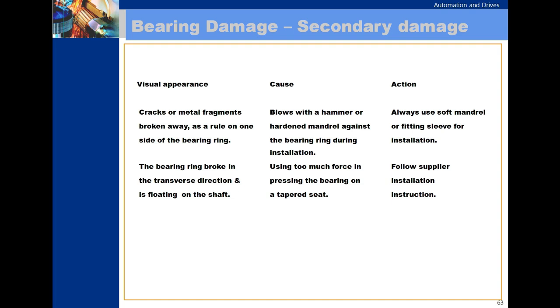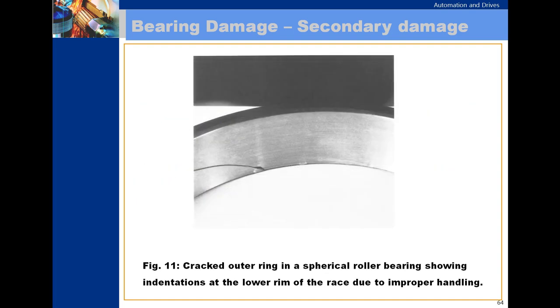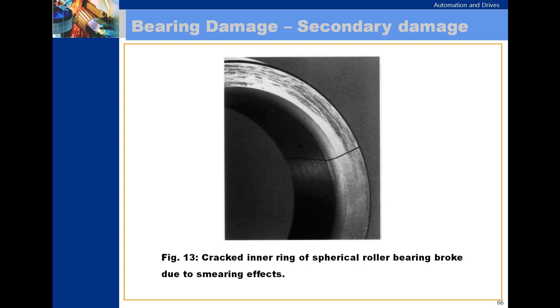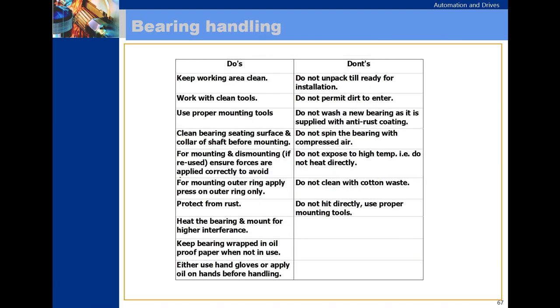Secondary damage: the cracked outer ring of a spherical roller bearing showing indentations at the lower rim of the race due to improper handling. Cracked inner ring of a spherical roller bearing. The cracked inner ring of the spherical roller bearing broke due to smearing effects. Bearing handling, dos and don'ts.